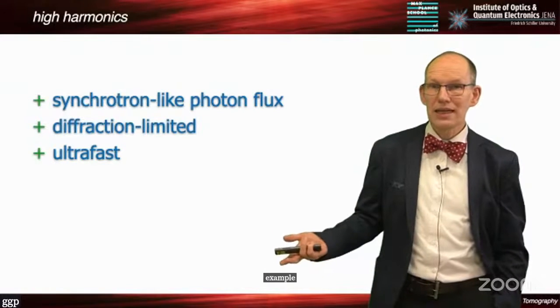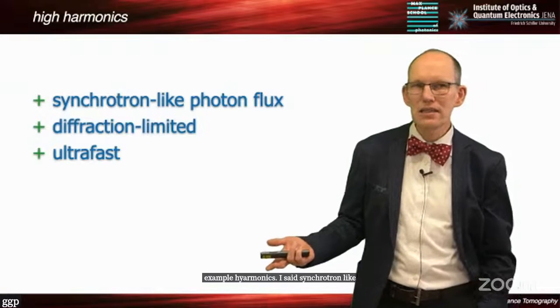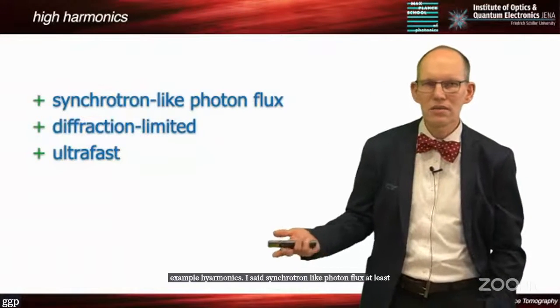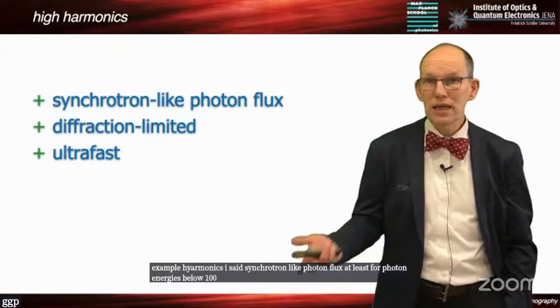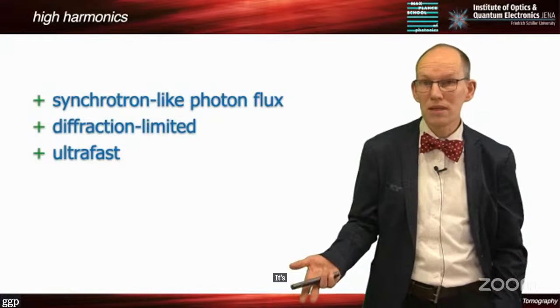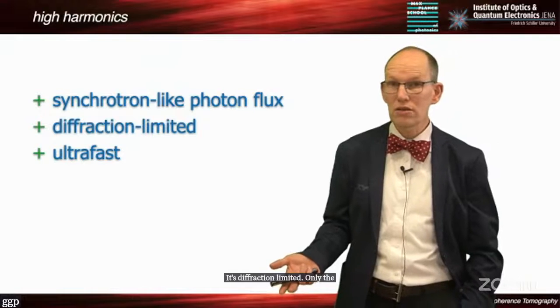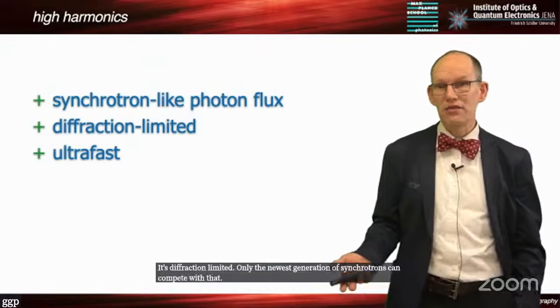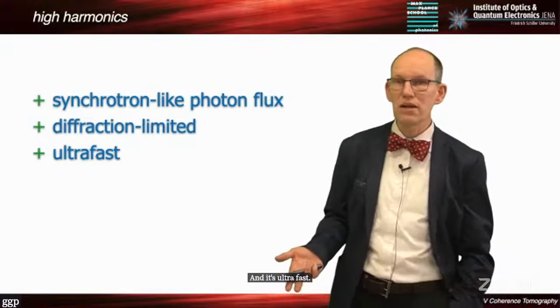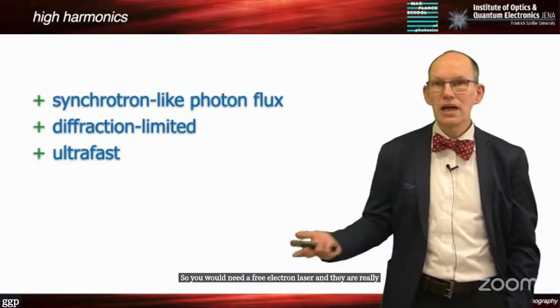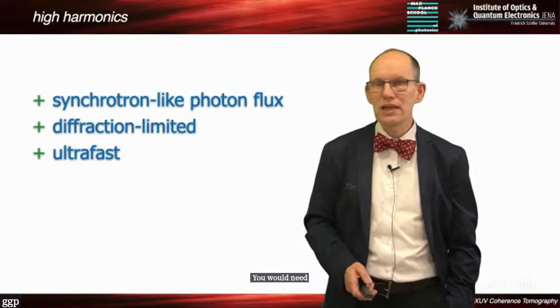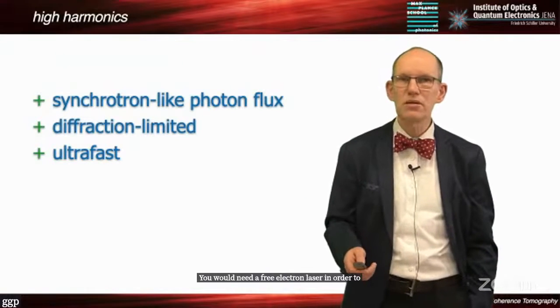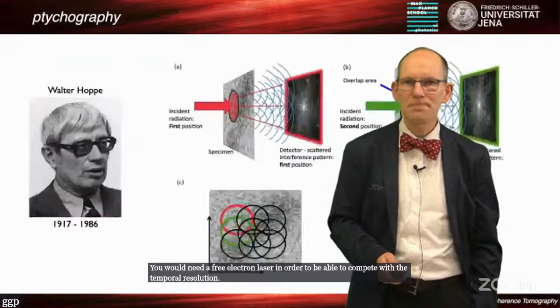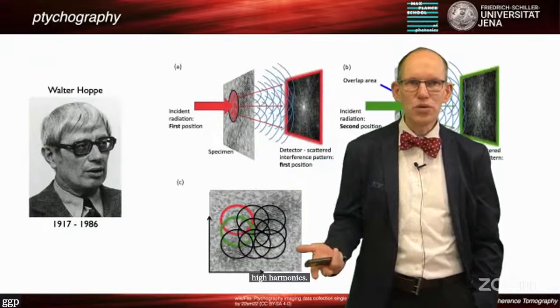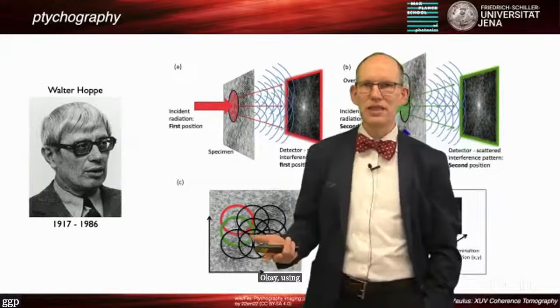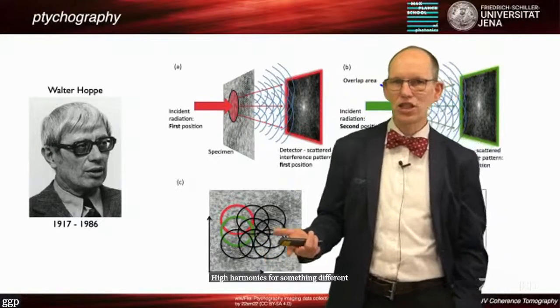High harmonics, I said, offer synchrotron-like photon flux, at least for photon energies below 100 electron volts. It's diffraction limited. Only the newest generation of synchrotrons can compete with that. And it's ultrafast. You would need a free electron laser, and they are really expensive, in order to be able to compete with the temporal resolution of high harmonics.